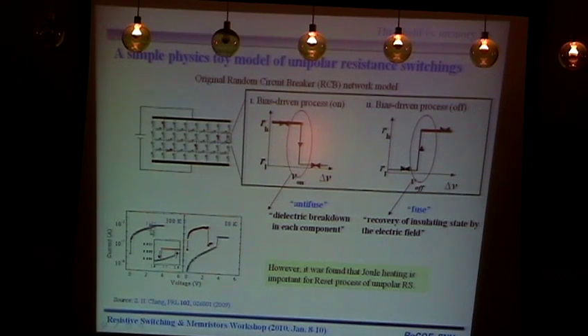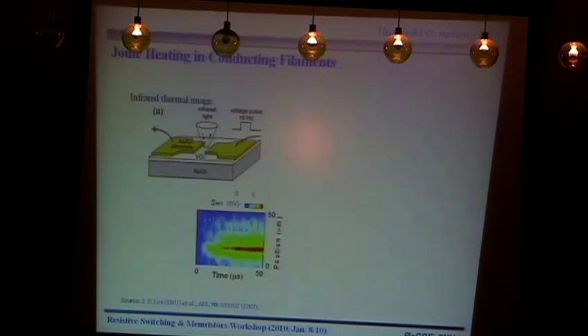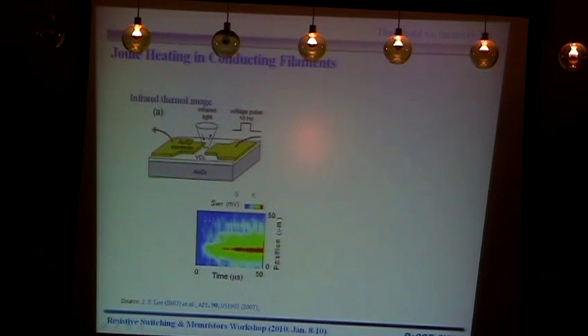However, I already showed this data. We have a thermal cycling between the threshold and the memory, which indicates that the joule heating should play a very important role in this kind of unipolar resistance switching. Also, earlier one of my former students did a very interesting work at a synchrotron radiation lab. He used VO2, which shows threshold switching. When it becomes metallic, he looked at the surface and measured the temperature. He found that a certain region has a much higher temperature, indicating that there is joule heating in this system.